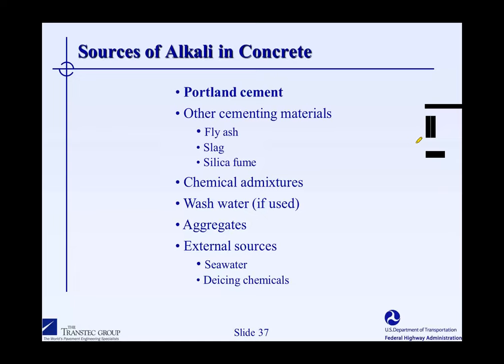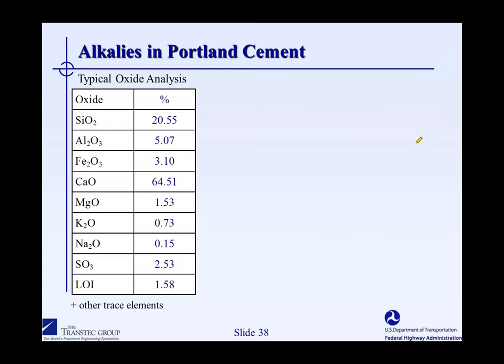And then, of course, we have external sources of alkalis that we might expose our concrete to. Seawater contains sodium. We put sodium chlorides onto our concrete as de-icing salts. And occasionally, we even put potassium-containing materials like potassium acetate onto our concretes. So we have to consider at least the exposure environment that the concrete's going into and whether or not we need to include those alkalis in the external environment when we're trying to assess the risk of reaction. But in summary of this slide here, I want to stress that it's mainly the Portland cement alkalis that are the main contributors to the expansion.